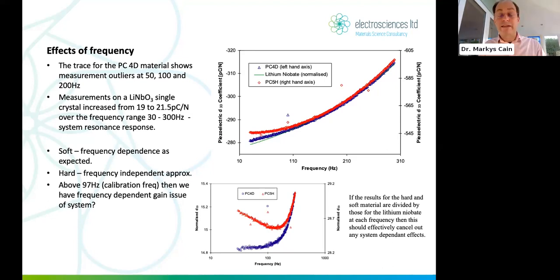You're moving large masses quickly, and you're going to have inertial charges, and you're not necessarily going to be able to equate the charges you are measuring with the forces that you don't know you're applying. Anyway, that's inertial forces. But when you do the subtraction, you can see real material property responses. Soft materials, as a function of frequency, you get a decrease in piezo coefficient, as you might expect for soft materials. Hard materials are fairly static, fairly linear.